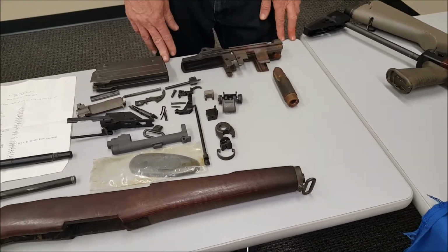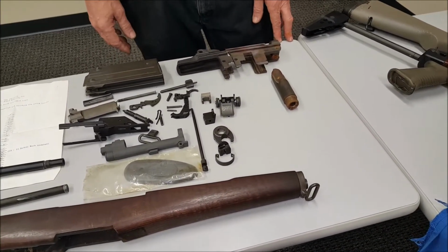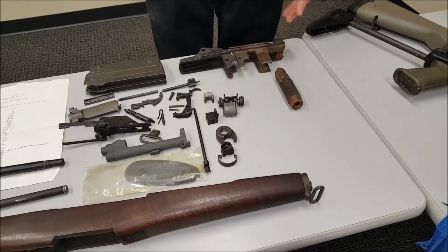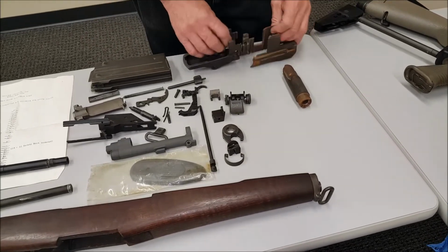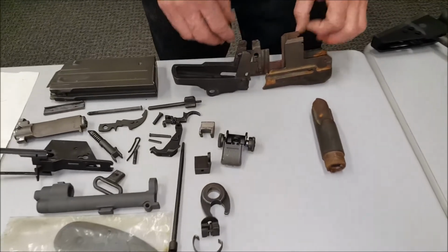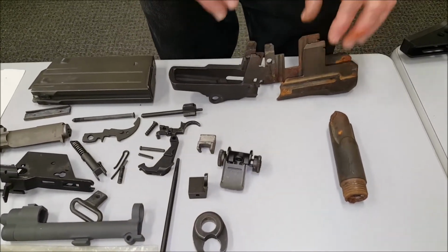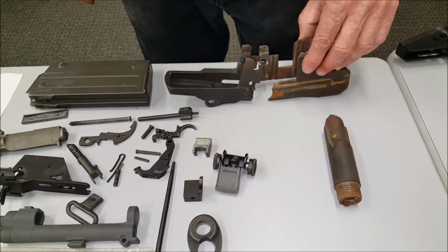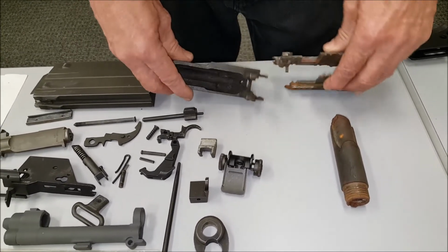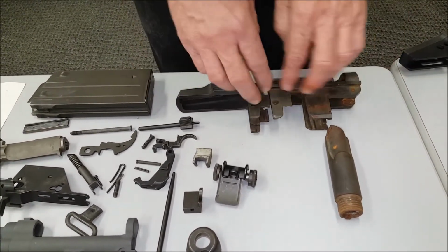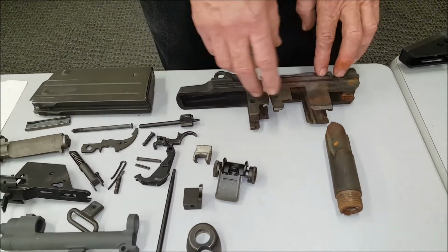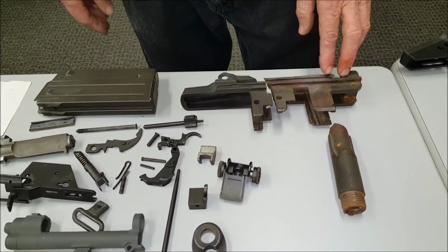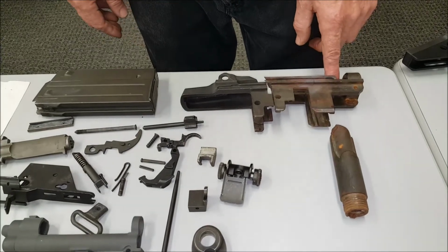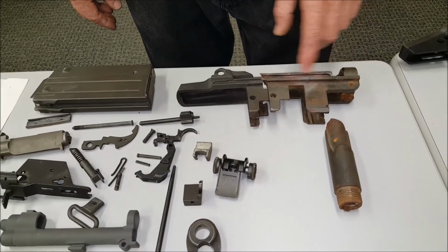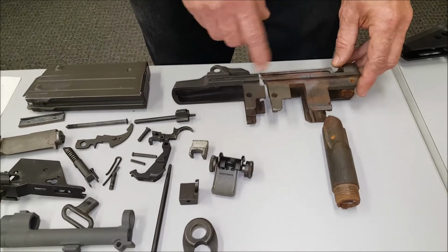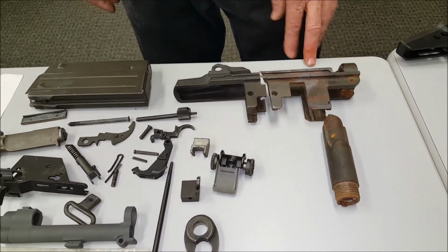Nowadays they mill them out with carbide cutters, so they don't anneal them and they don't have to reheat treat them. But you've got to remember, anytime you're taking more than a couple thousandths off any part of the receiver, you're cutting down into that softer material, and you're losing your surface hardness. In non-stressed areas where you're doing most of your modification, it doesn't really matter. But when you're dealing with your bolt locking lugs or your op rod guide slot, hardness does matter.